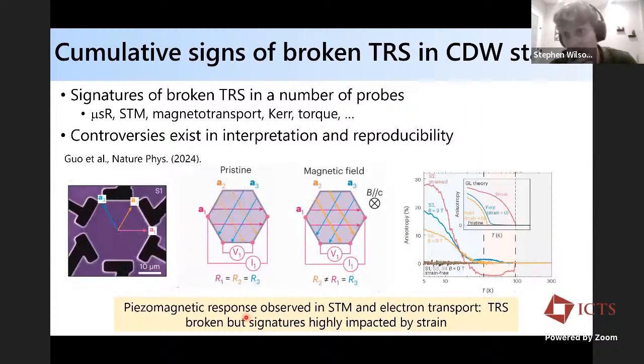And then in parallel, similar work by Philip Moll's group, where they create a small device. What they showed is that when you take cesium vanadium 3 antimony 5, prepare it in a strain-free state, and look in the charge density wave phase, you find that you don't have any in-plane transport anisotropy, okay? But if you apply an out-of-plane magnetic field, then transport anisotropy turns on. This is also consistent with a hidden piezomagnetic response in this system. And that goes to the fact that these systems can be highly sensitive to strain, unintentional strain or defects in crystals. As part of my talk, I'll be showing you the metastability and the impact of strain on the charge correlations of these systems.